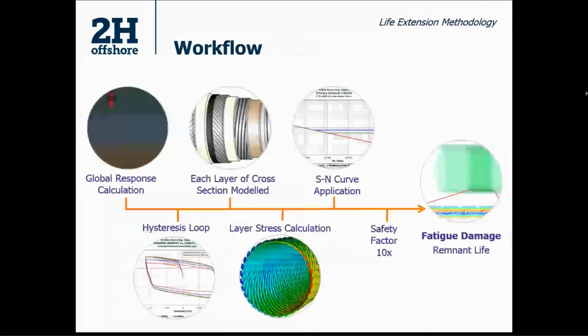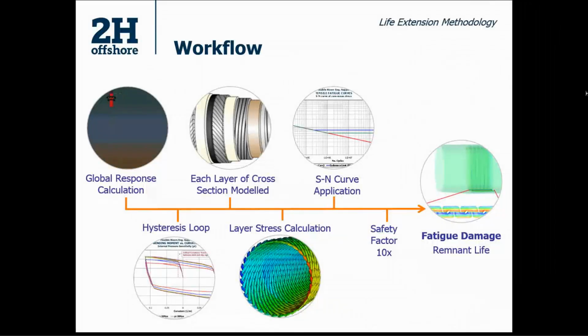So this is how the overall workflow looks. The global response calculation is done, modeling the system as a whole, with the pipe being modeled in a homogeneous way, and then into a little bit more detail modeling. The local model is created and the hysteresis loop is incorporated. So those first three circles are a bit of an iterative process. So we use the local model to calculate the hysteresis response. Then we feed that back into the global response and make sure that that's been captured. So then we get an appropriate combination of tension and curvature.